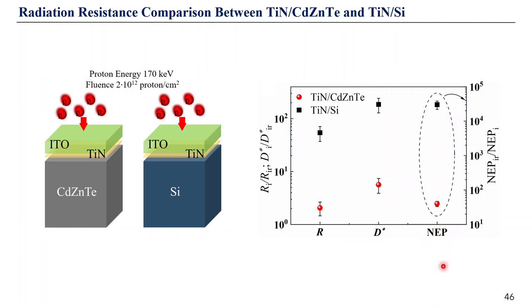NEP stands for the minimum optical signal power which can be distinguished by the photodiode due to the noise-to-signal ratio, and it's determined by taking the ratio between the experimentally measured noise current spectral density and responsivity. So we see that our titanium nitride cadmium zinc telluride heterojunction exceeds in radiation resistance its silicon counterpart by orders of magnitude. So that means our photodiode can operate under harsh ionizing radiation conditions much longer.